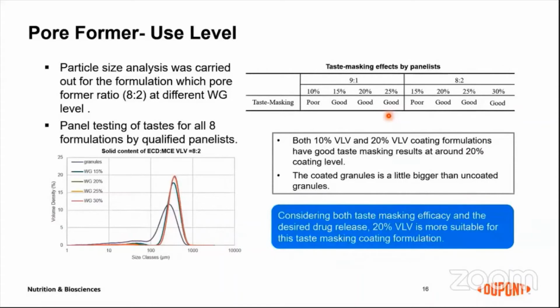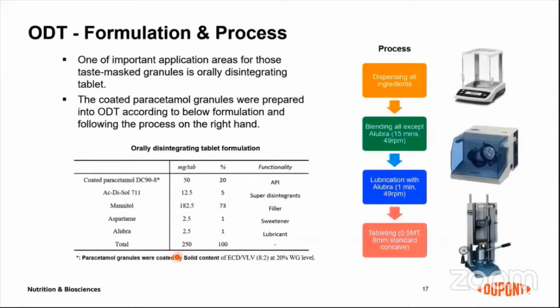So actually, when we take a look at both taste masking efficacy and the desired drug release, 20% of VLV is more suitable for this taste masking coating formulation. And after the coating, the coated granules are a little bit bigger than uncoated granules, but it's not a very significant change. So we can see the particle size distribution data here. Right. And then we move to the ODT formulation and process.